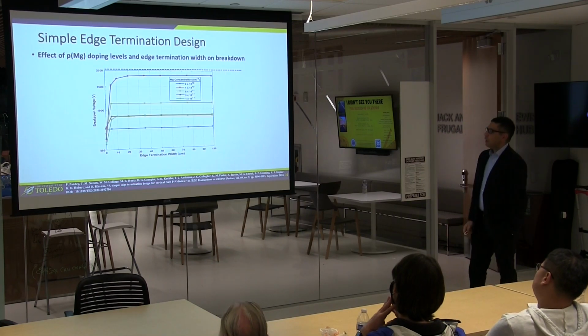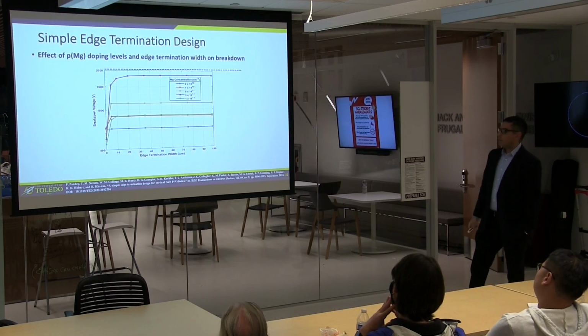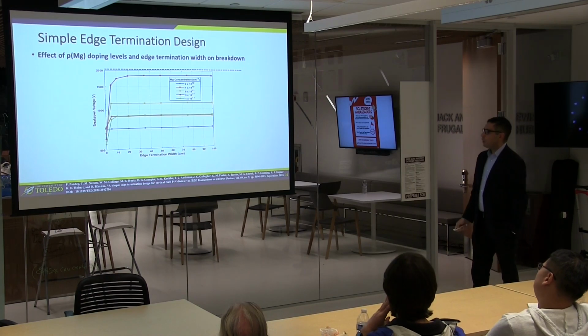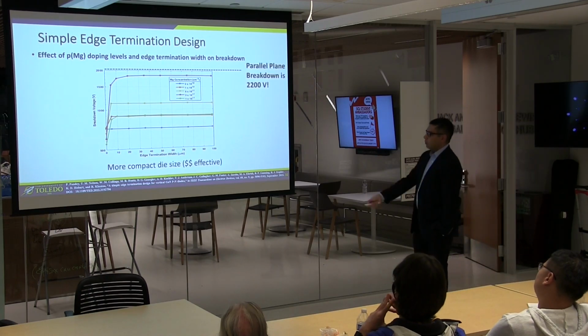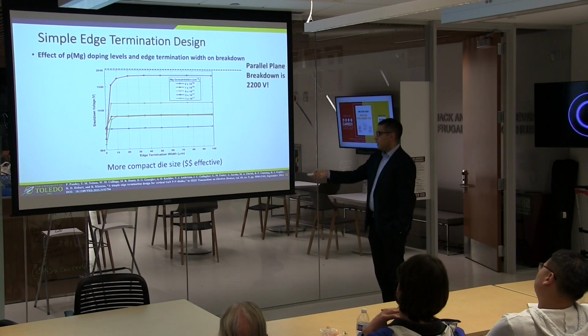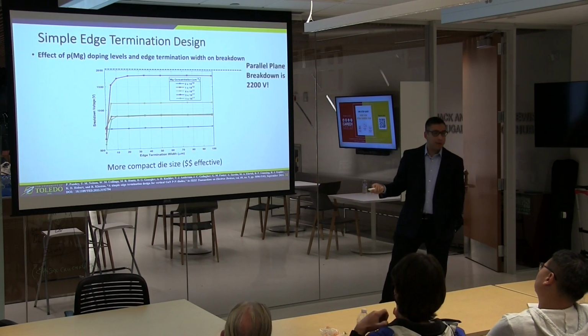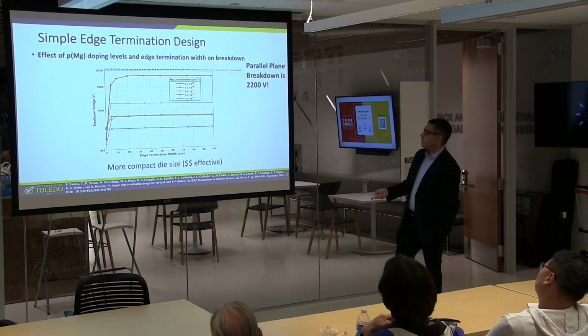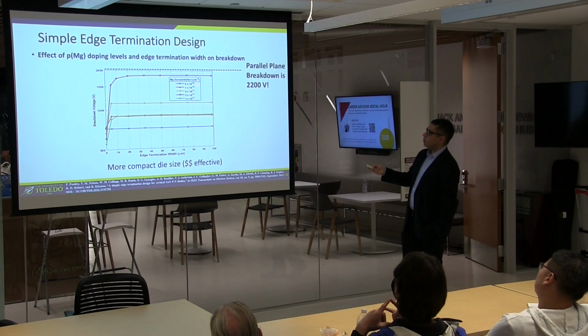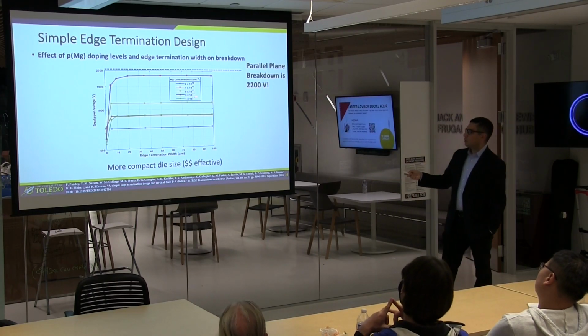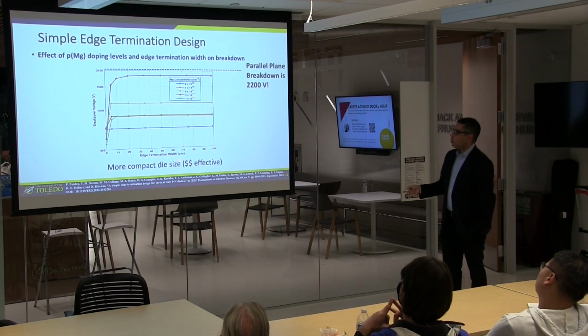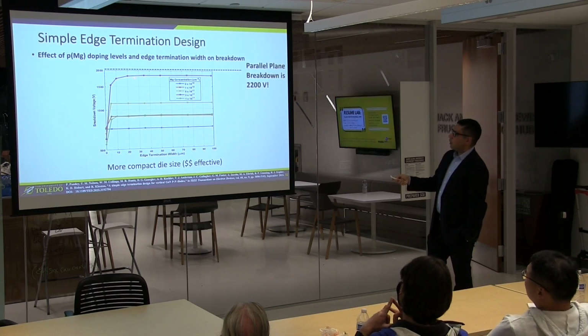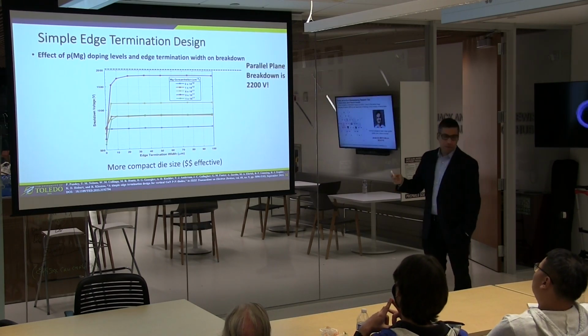What about the edge termination width? That's important for the die size. The die size impacts the cost of the device. So I call your attention to this purple curve here. This purple curve is again at an Mg concentration of 3 × 10^17. What we're saying is for an edge termination width of 20 microns all the way out to 100 microns, you're getting almost the same breakdown voltage, and very, very close to the parallel plane breakdown.